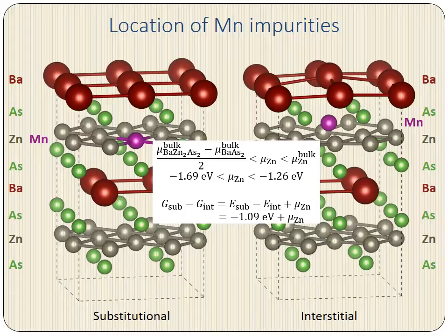As you can clearly see, if you plug the range of the chemical potential of zinc into our free energy difference, we see that the substitutional impurity is highly energetically preferred over the interstitial one. That means, for all intents and purposes, interstitial impurities simply do not appear within this system, and for the rest of our talk, we're not going to consider them in any subsequent analysis.